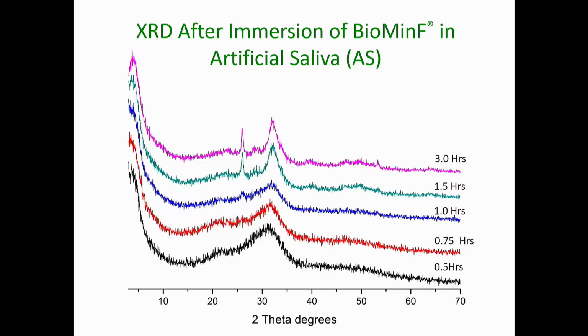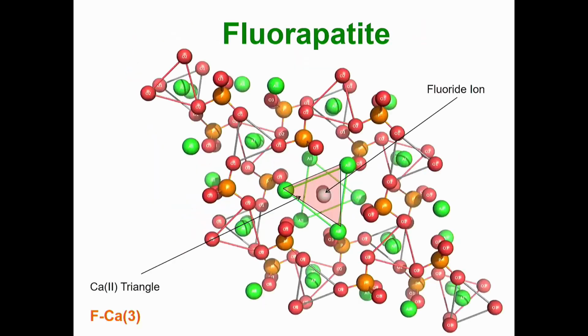So here we have some X-ray diffraction patterns of the Biomin F glass after immersion in artificial saliva. And what we can see is the development of the characteristic sharp diffraction peaks for apatite, which start at about an hour. It was important for us to demonstrate that the Biomin F and the fluoride bioglasses formed apatite.